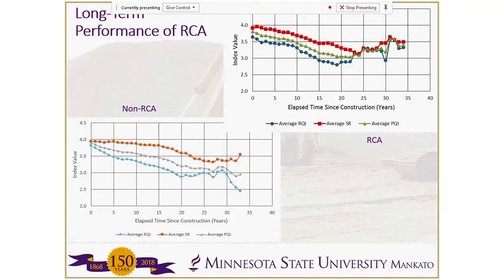A typical trigger value for major repair is like 2.5 on the ride quality index. So we can see that RQI in most cases seems to be the one that will deteriorate first and cause the trigger for major repair. Also, just to point out that towards the end, it looks like on those graphs there's a slight uptick. It's actually getting better. The reason for that is that by that time some pavements have been repaired already. So the RQI index values are going up higher, which is causing it to look as if they're improving with time at the end.